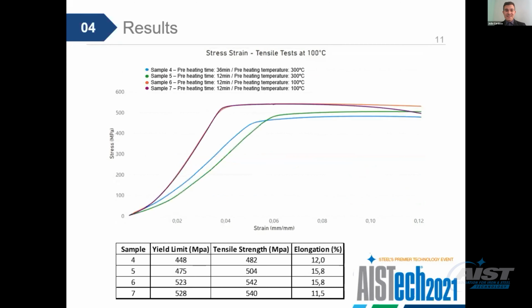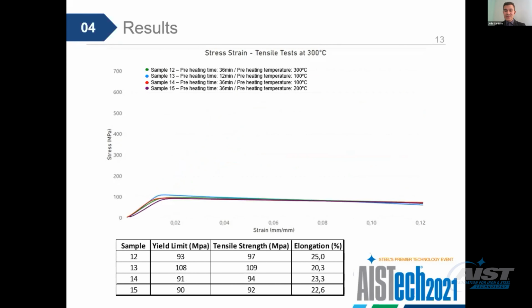And as you can see, since the beginning, there is a huge progressive decrease in the mechanical properties, reaching more than 80% of reduction in the yield limit, comparing to the test at the room temperature.